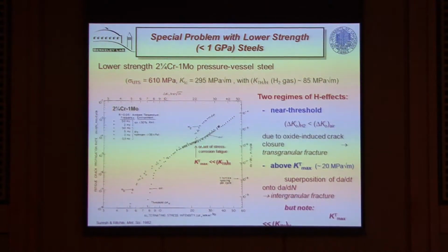And the point is that this is the same sort of stress intensities you see in high-strength steels. So low-strength steels are as susceptible to hydrogen embrittlement under cyclic loading. But you wouldn't realize that if you were looking at under non-cyclic conditions. Now, why is that? And the reason is that in these lower-strength steels, the crack tends to blunt.